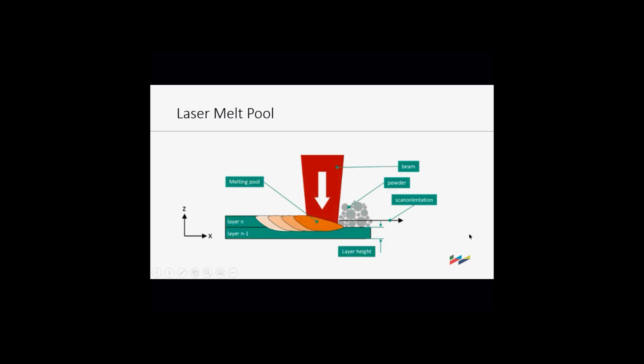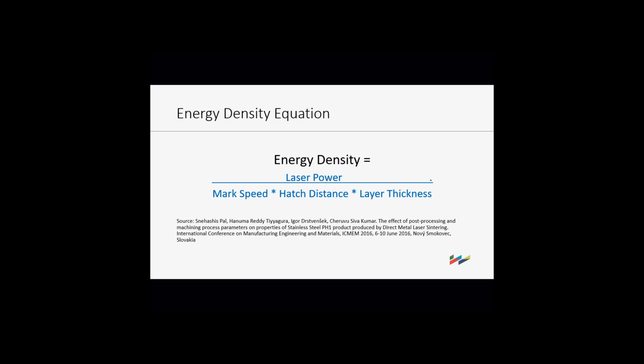Okay. And so as the laser's going down, it's expanding, going down. You have to do an overlap here, because if you don't, you have powder there, and then you've got everything fall apart, right? And so you have to melt in the next layer, but you don't want to melt too far down, because then you're losing a lot of energy. So this is basically lasers going across. You've got powder here, and then as it melts, it develops this, and it cools as you go by.